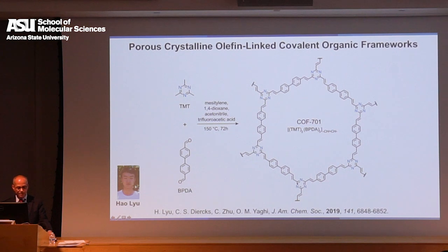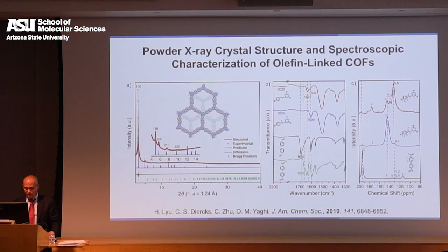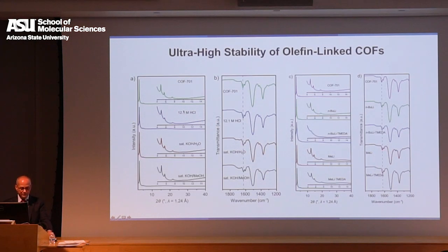These are all very strong bonds. This is an amazing structure. No one would have predicted that you can do this under 150 degrees, under such mild conditions, or at all, actually. Because if you go to a very high temperature, you're going to decompose your COF. So this is the X-ray powder diffraction, and you can see that we use spectroscopy, NMR and IR, to make sure that the right linkages are being made. But look at the stability. You can take this COF and put it in concentrated HCl, saturated KOH, in water, in methanol, do whatever you want. Put it in corrosive n-butyllithium, and the structure is unaffected. And that's what we expected with carbon-carbon bonded frameworks, okay?